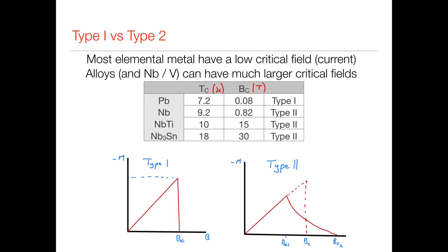For something like lead, the critical field is actually tiny. It's 0.08 Tesla. So for most elemental metals, the amount of field that it can sustain, and hence the amount of current it can sustain, is really very low. So elemental metals are typically not very good for any current carrying application. You could only make a very weak magnet out of some lead superconducting wires.